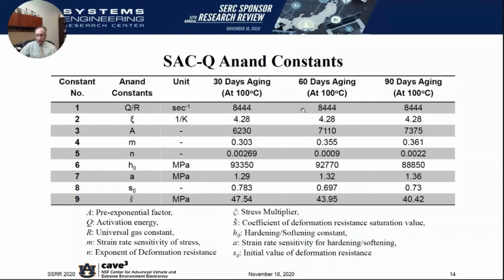So we have a set of material constants versus different durations of isothermal storage. The intent is to actually capture this data for up to 1 year of thermal storage to replicate the risk with using some of these newer doped alloys in the end application. But right now we have about 90 days of data that the samples have been tested for. The remaining samples are in test right now, where they are in thermal chambers for extraction at the end of the 1 year period, and then they'll go into test. So this is an ongoing test, and we are presenting an interim snapshot of our progress.